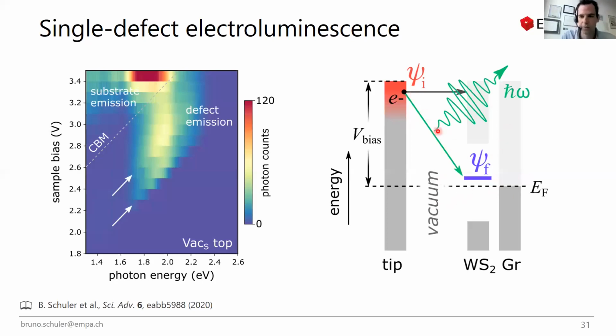And this transition becomes more likely if the photon density of states at this frequency, so that energy difference that connects your initial and your final state, is high in your cavity. And the photon density of states is mainly, in our case, composed of our plasmonic tip. Because we poke our tip into the gold first, we will have a gold coated tip. And this defines the emission energies which we are likely seeing. And that's actually also the case.